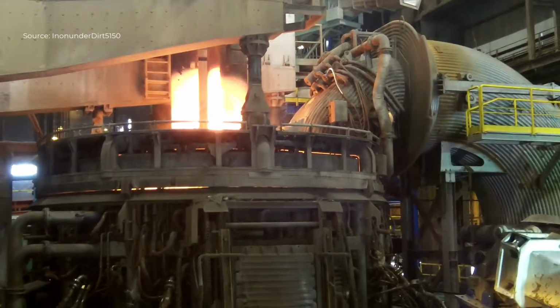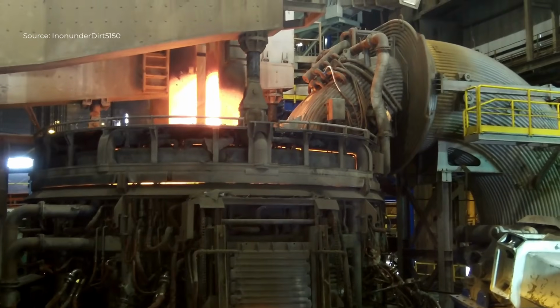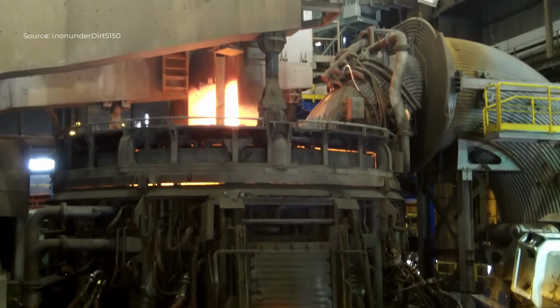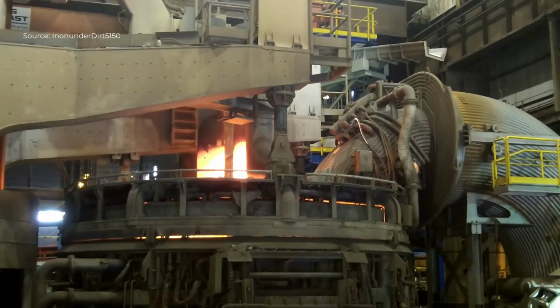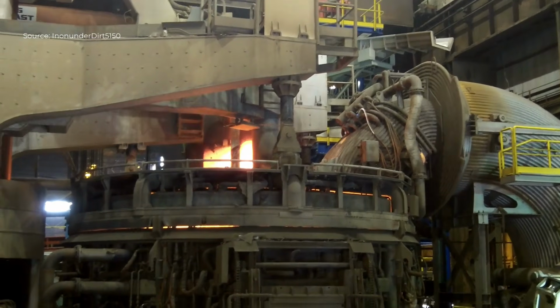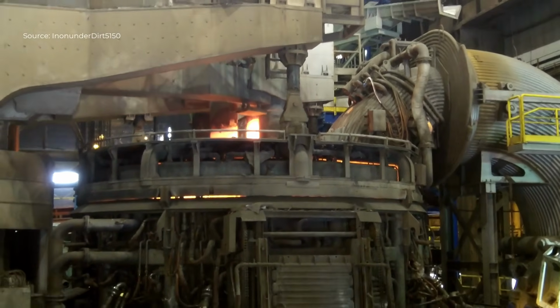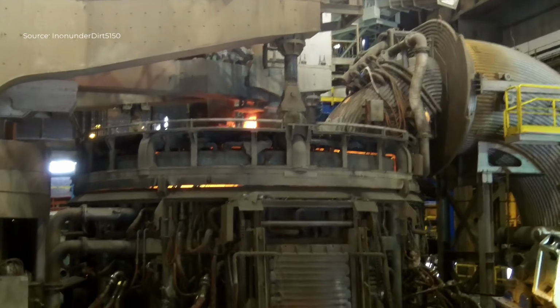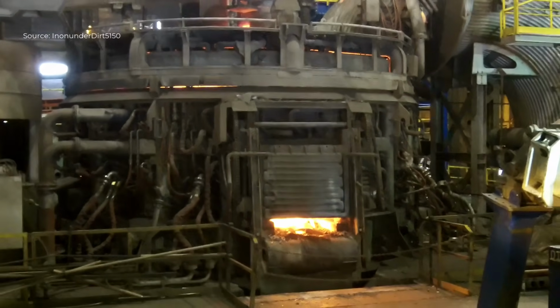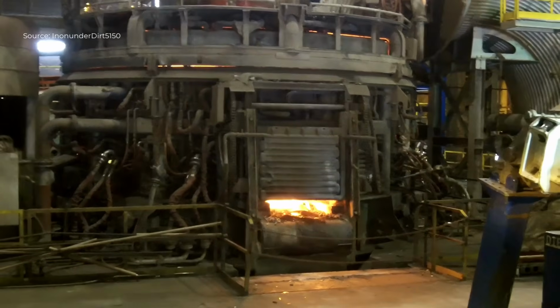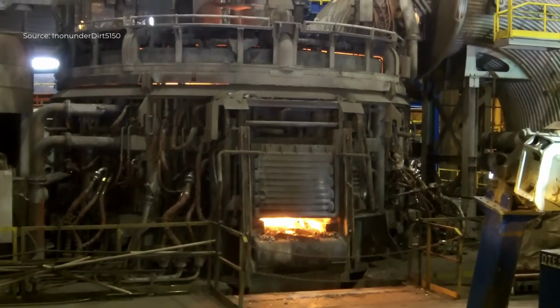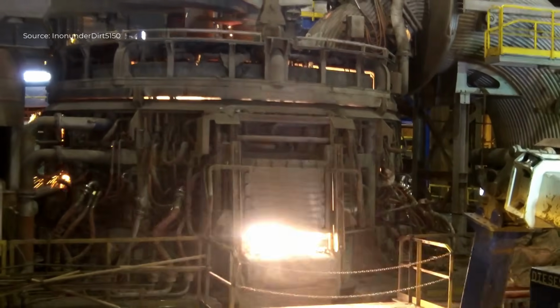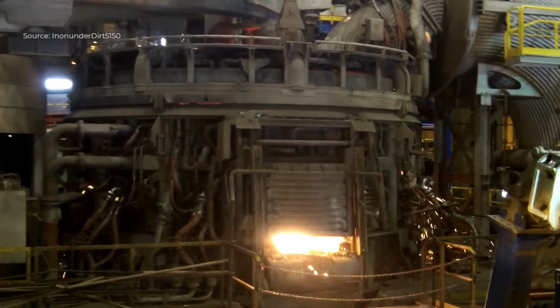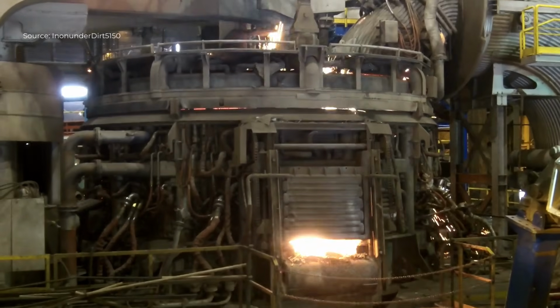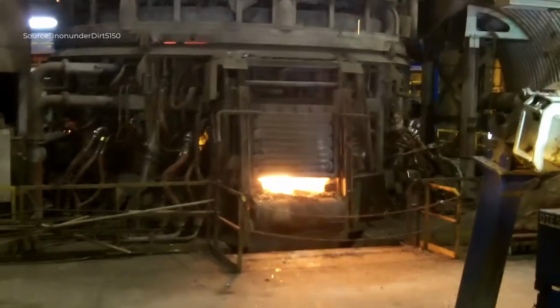An electric arc furnace, or EAF, is a powerful industrial installation designed to produce steel by melting scrap metal through intense electrical energy. The furnace operates by generating high-temperature electric arcs between graphite electrodes and the metallic charge placed inside a refractory-lined vessel. When the electrodes are lowered, electric current flows and creates arcs that heat the material to temperatures above 1600 degrees Celsius.